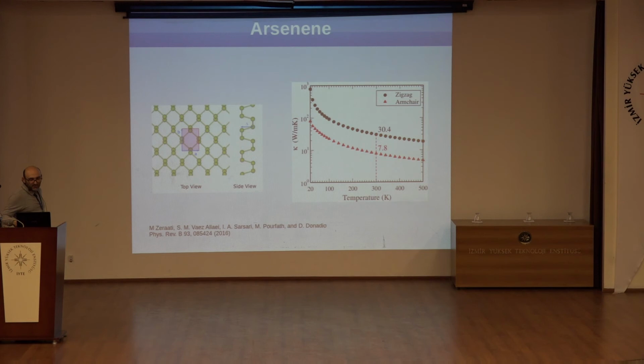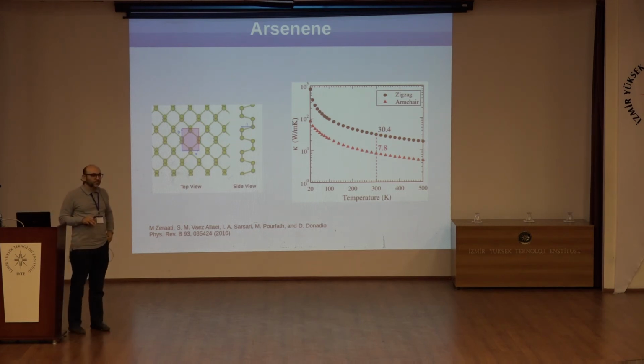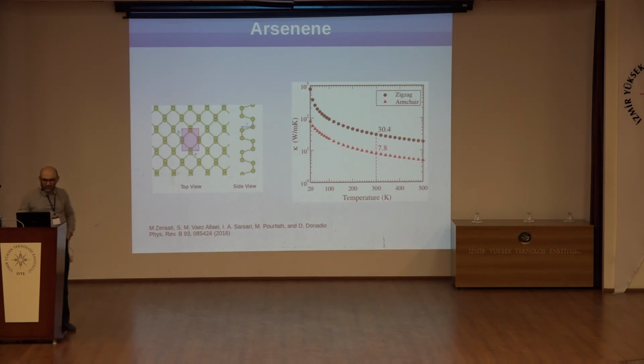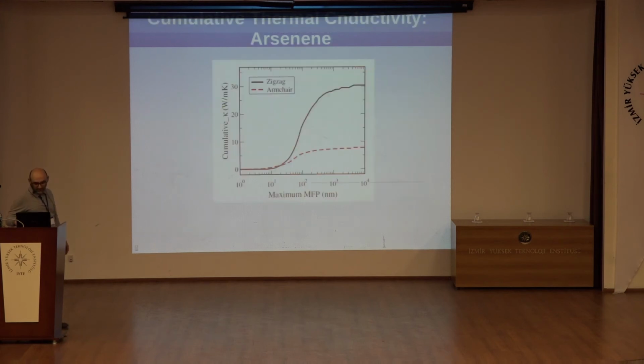And also we studied the two-dimensional case of arsenene. In this case, we have a highly anisotropic thermal conductivity that is possible to consider in heat management especially, and at the same time we have low thermal conductivity that might be possible to consider in thermoelectric effects as well. This is the cumulative thermal conductivity that we have obtained for the arsenene case, and the contribution of different modes in thermal conductivity has been shown.